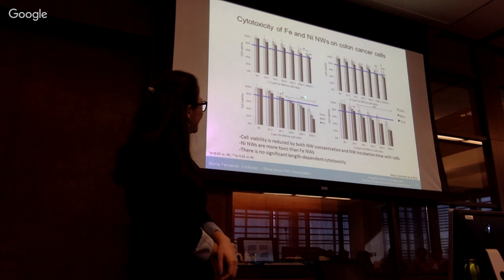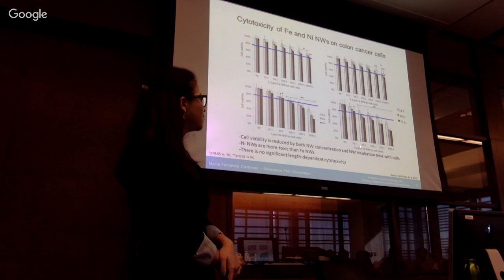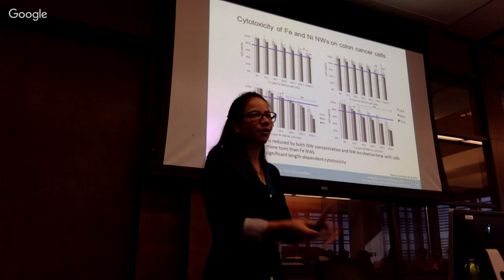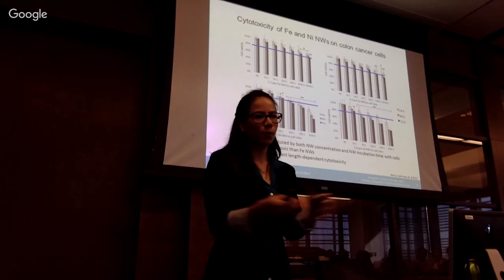If you think about it, we are adding here 5 times or 4 times more material, but you don't see things dropping 5 times or 4 times. So there is not a strong correlation between the length of the wires and the toxicity to the cells. Okay, what about the nickel ions? If we focus on the nickel ions, what's their part in this whole toxicity story?